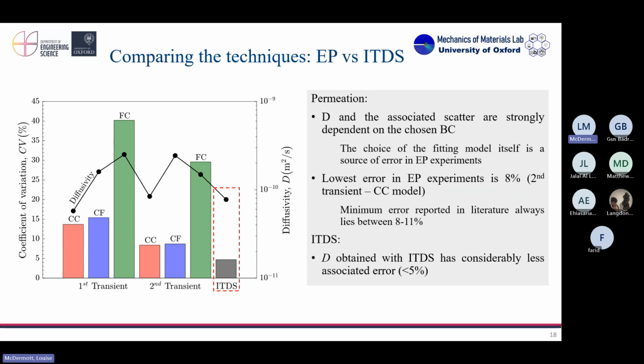So let's look first at the coefficient of variation. What we can see is that in permeation, the coefficient of variation depends a lot on the boundary condition that I choose. It is at its minimum when I assume a constant concentration of hydrogen on the entry side, and in the second transient, where I don't have trapping effects. If I compare the diffusivities, I have very unusually high diffusivities for this boundary condition, this one and this one, and very similar values between this one and this one. So to have some kind of reliability in permeation, I need to do more than one transient to remove trapping effects, and I need to assume, in this case, constant concentration of hydrogen on the entry side of the sample.